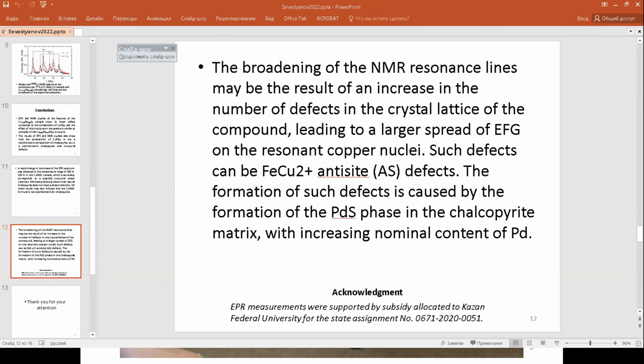The broadening of the NMR resonance lines may be the result of an increase in the number of defects in the crystal lattice of the compound, leading to a large spread of EFG of the resonant copper nuclei. Such defects can be Fe-Cu2+ anti-site defects. The formation of such defects is caused by the formation of the palladium sulfur phase in the chalcopyrite matrix with increasing nominal content of palladium.